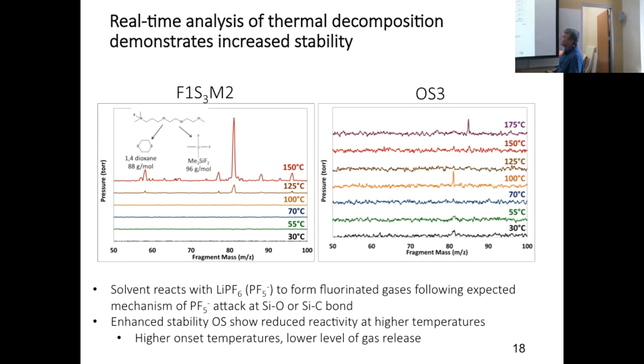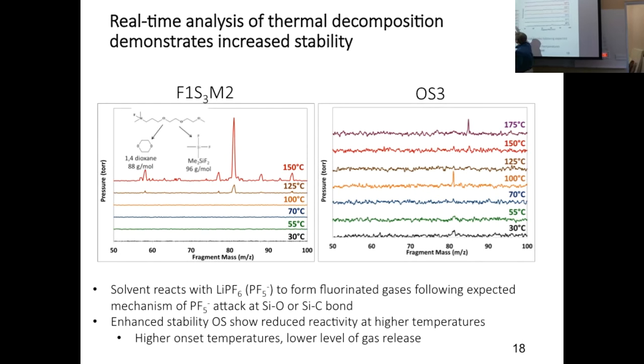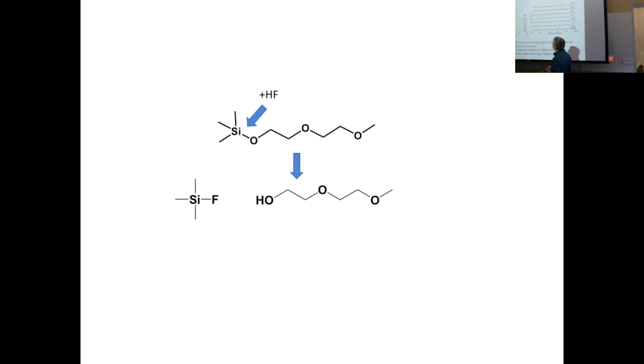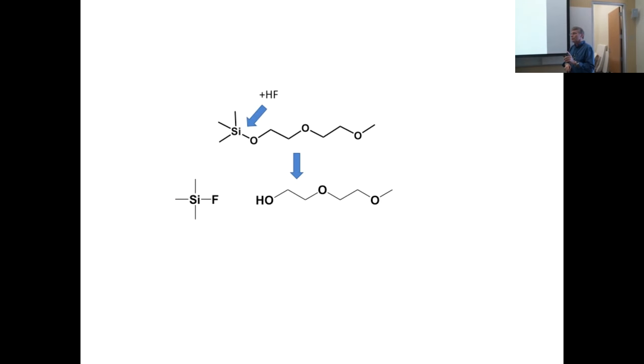We have these little codes we use to designate sort of what the structure is, but that's not super important. Okay, so the challenge here then is that this sort of Gen 1 set of compounds didn't work well, not because it was intrinsically bad, but because you always have a little bit of HF present. And the challenge here is that you can't make an electrolyte really, really dry. So a typical battery-grade electrolyte has about 30 parts per million of water in it, which isn't very much.